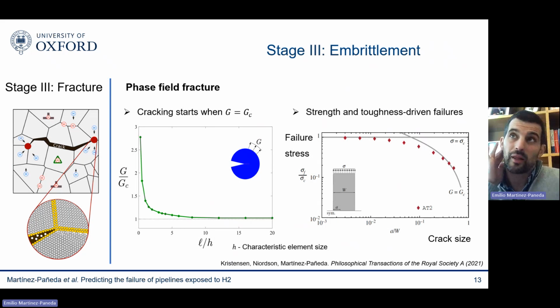And as I said, the length scale also comes into play, and the length scale governs the strength of the material. There's a closed form expression for that, and therefore you are able to capture not only toughness dominated failures. This is, by the way, failure stress versus crack size, and you can see that we capture this well-known concept in fracture mechanics of the transition flaw size that is widely used, for example, in standards such as the R6. So you go from toughness dominated failures, where again you can see a very good agreement with analytical predictions coming from linear elastic fracture mechanics, all the way to the situation where you get plastic collapse or strength dominated failures. So the model can naturally transition from one to the other because you're inputting the toughness and the